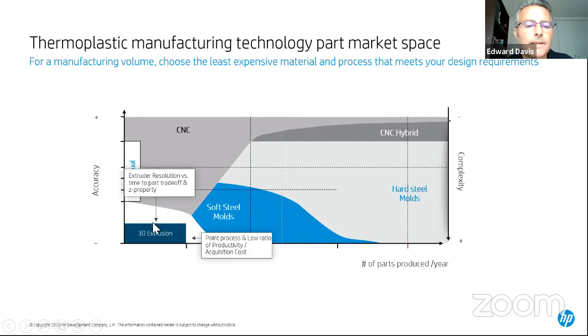And then scaling to better tolerance, they actually have a trade-off. The bore diameter for that extrusion is a trade-off between, do you want to go fast or do you want to have fine detail? If you got a big bore, you can go really fast, but you got terrible detail. If you have a very small bore, you can get great detail, but you have terrible productivity. And this is algebra, right? If you want to control two things on the output, you need at least two input variables, and they have one input variable while they have a single diameter bore. And so they're forced into a trade-off, and they picked a point which is not terrible detail, not terrible productivity, somewhere in between.